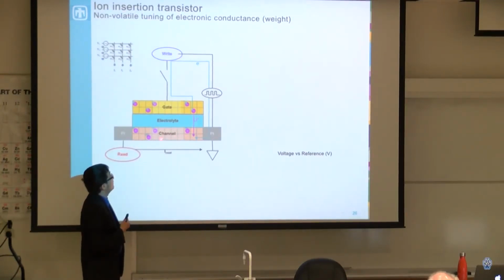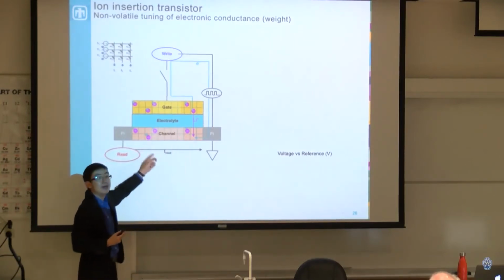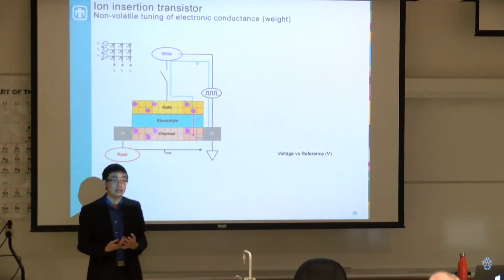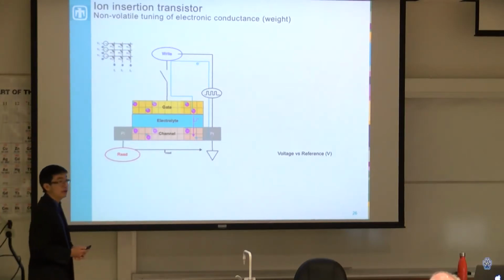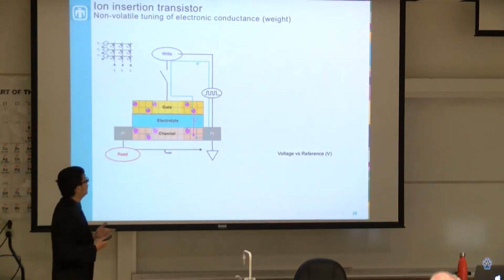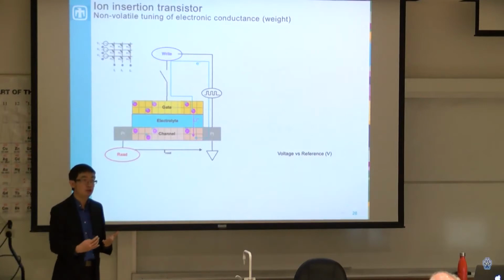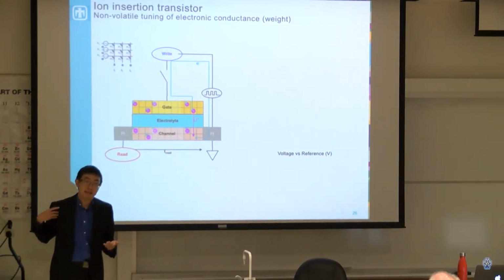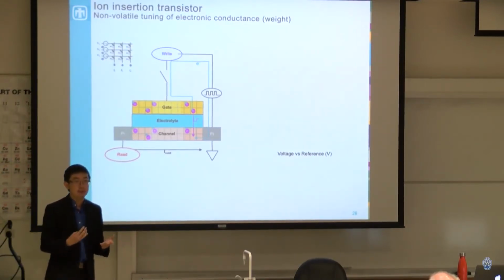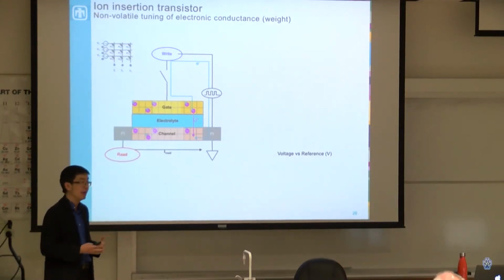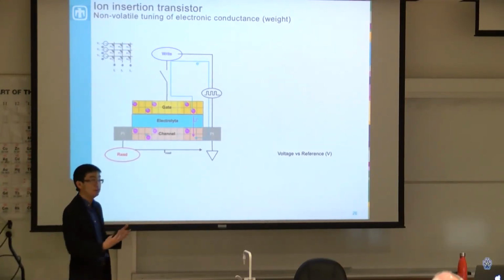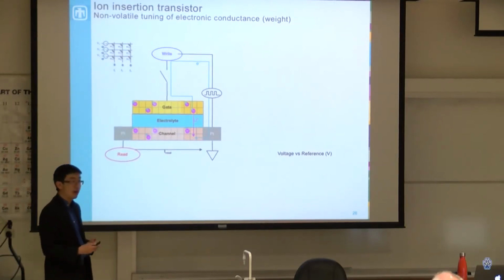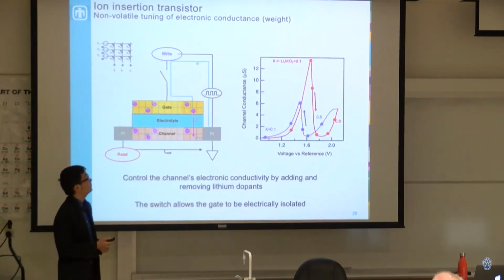And by moving lithium ions, we change the amount of electrons at the bottom here. As a result, we can change the electronic conductivity of this material. So this transistor operates on a process of moving dopants. Whereas in the semiconductor world, dopants are usually something you put into your material during fabrication to change the Fermi energy, here we're actually moving dopants in the material to change the conductivity in real time.